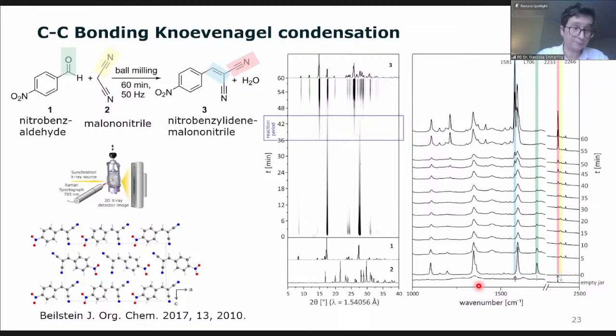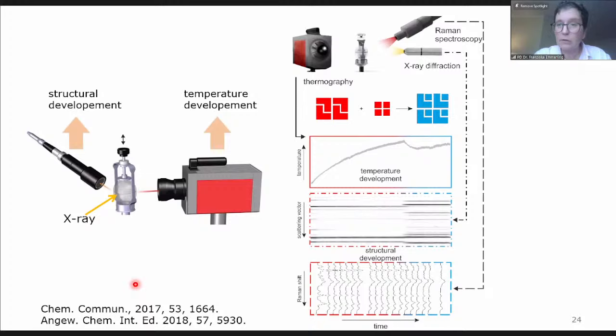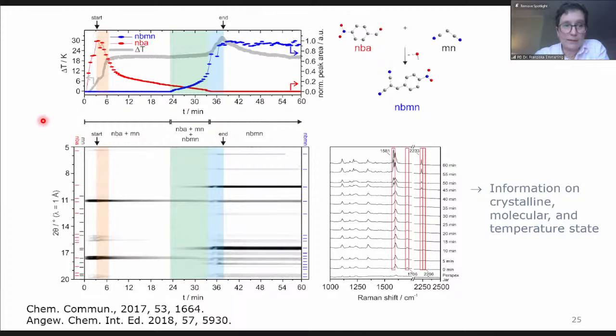Okay, that was a nice setup. And then we thought, if we can add two methods, we can add another one. And here we added thermography. So we also get temperature information of our vessel, monitoring the temperature during the reaction. Here you see more or less the same data I showed before, just now tilted by 90 degrees. So this is our diffraction pattern. And if you follow this temperature curve, the gray curve here, we have an increase in temperature at the beginning, and we reach a plateau.